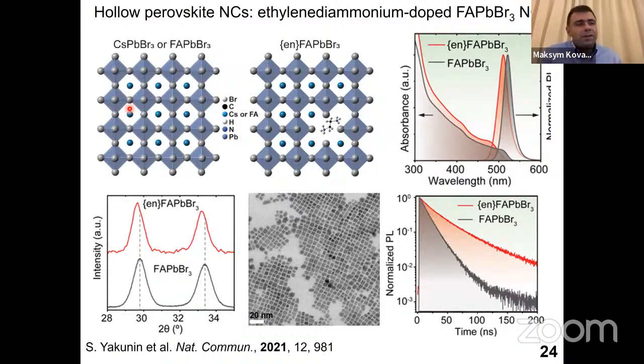Let me show you another aspect which is possible with perovskites and not easy to do with anything else, which is that now you can also engineer the perovskite itself. The perovskite lattice is very soft. So you can actually displace some of your inorganic constituents with organic ones, maintaining the lattice. So the lattice will not collapse even if you displace up to 10% of the core material by another organic material. And so you can keep the nanocrystal size, but you will drastically modify the electronic structure. For example, you can actually engineer such materials, these hollow perovskite materials, what you see on the screen, that will have exactly the same emission color, but different radiative rates.